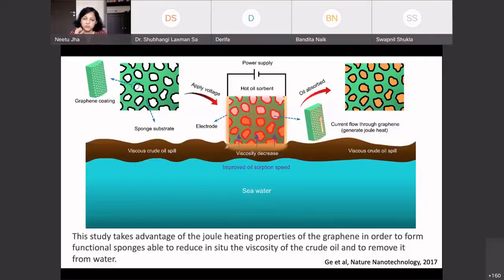Now the problem which was being faced is that the viscosity of oil is very high, so it takes a lot of time in filling up all these pores. That can be reduced by using Joule heating, because thermal conductivity of this graphene is very high, and you can use heat. We know that with heating the viscosity reduces. If viscosity reduces, then the transport increases. If transport increases, we can easily fill these pores with oil. So this is an example from this paper, if you want to know more detail about it, you can go to this paper, where graphene is coated on the sponge.